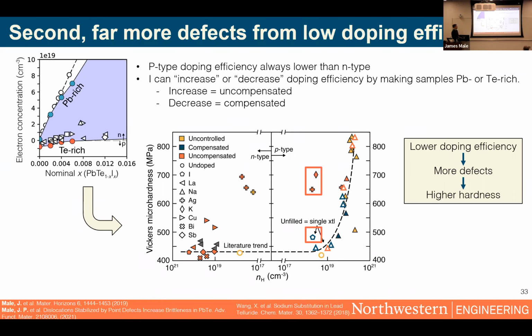So if I wanted to get like 5 times 10 to the 19 carriers with iodine, I have to add about 0.2 atomic percent to achieve that. With sodium doping, I need an order of magnitude more doping. So essentially what that means is I have many times more doping defects in the P-type samples. And also because the low doping efficiency exists, I have many more times compensating intrinsic defects. So the gist is that lower doping efficiency gives you more point defects and raises hardness by point defect dislocation interactions.